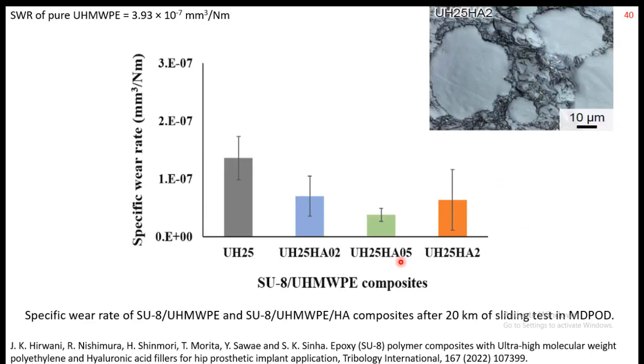We compared the wear rate, and even though there's a lot of scatter in this kind of evaluation, our composite of 25% UHMWPE and 0.02 or 0.05 HA gives a low wear rate compared to pure UHMWPE, which gives 3.93 times 10 to the power minus 7 - much higher than our composites.